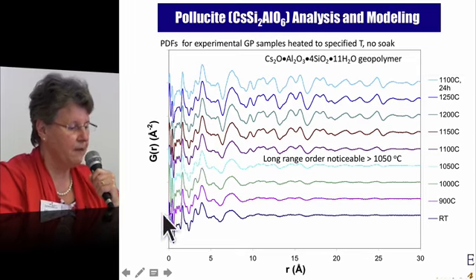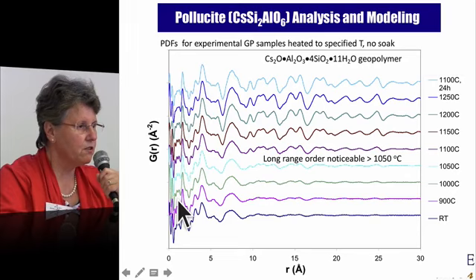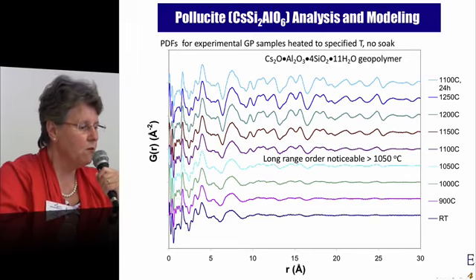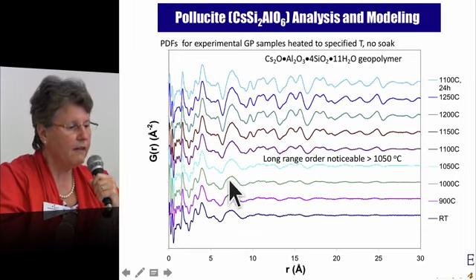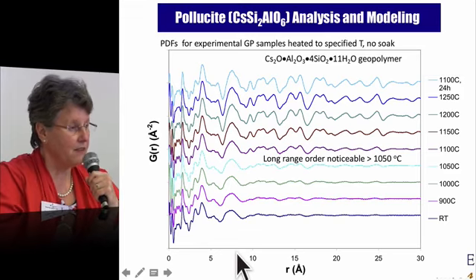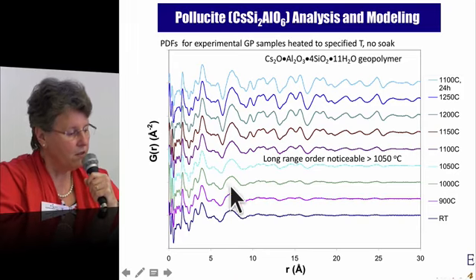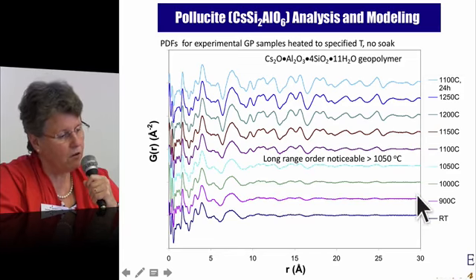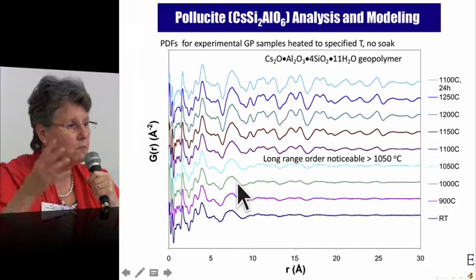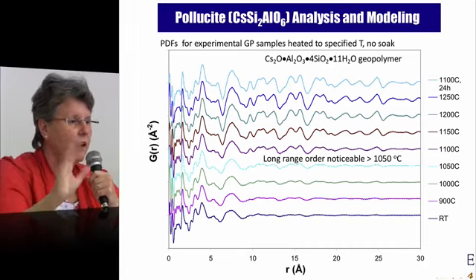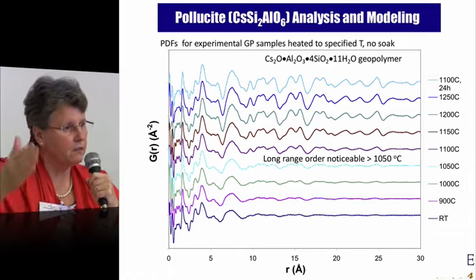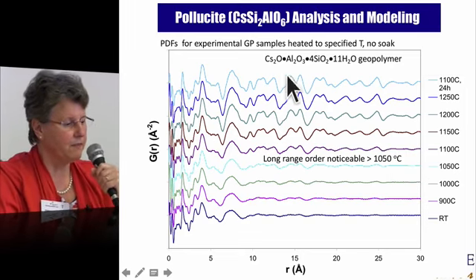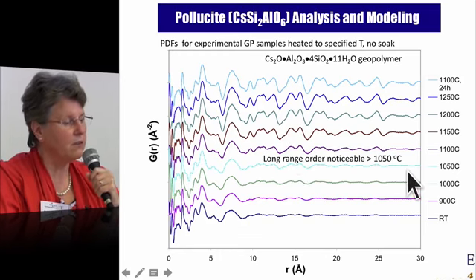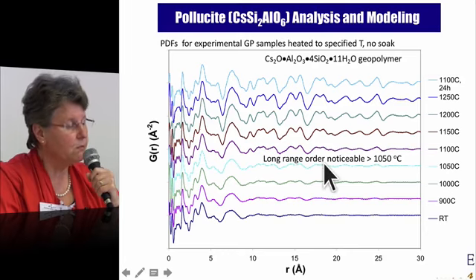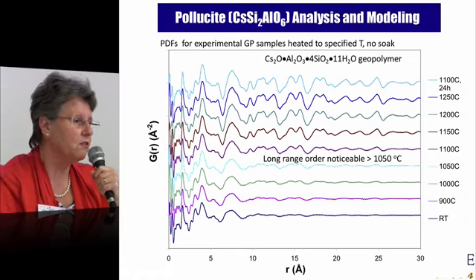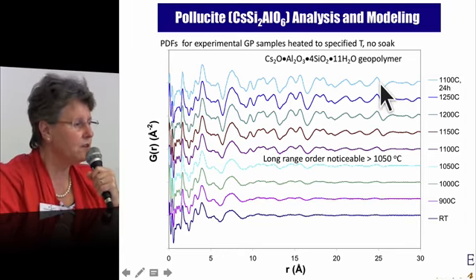And basically it says that even at room temperature you've got characteristic units of tetrahedra, AlO4 minus and SiO4 tetrahedra, and in the case of cesium as a charge balancing cation, you can get it out to about 7 angstroms, and you got these tetrahedra building blocks already in place, but they have no long range order. So you got polymers, but there's snakes in a box going everywhere, and if you want to crystallize them, they're all supposed to lie down straight. So if you want to crystallize like this material, which is called pollucite, you have to heat to 1000 C. So this real geopolymer is stable to 1000, and then the worst thing it can do is crystallize, and then pollucite melts at 1940 C.